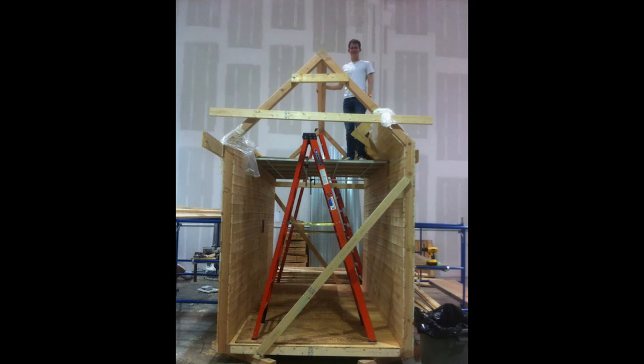So one of my favorite projects I wanted to share here is that we actually grew a building at Ecovative. And I live off-grid at home, and I also grew a building, and it works quite well. This is something you really can't do because of building codes. You know, code is very prescriptive, so you're really funneled into certain ways of building. When we sell our insulation, we dry it, and we kill it, and we get it ASTM tested to prove that it's dead. But really, our insulation works better if it's sort of dehydrated and semi-alive. That way, if it gets wet, it doesn't mold, it reanimates and fights off the competitor. That's a better process, but that's way outside the scope of how architects, designers, and especially the building inspector expects materials to behave.